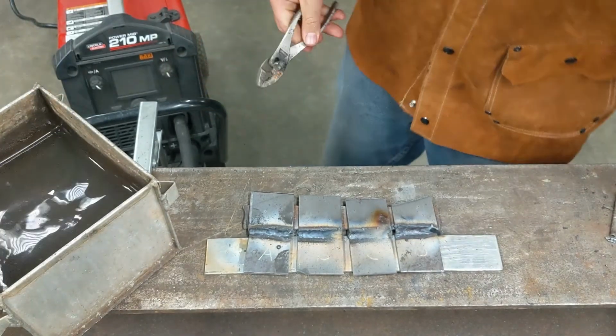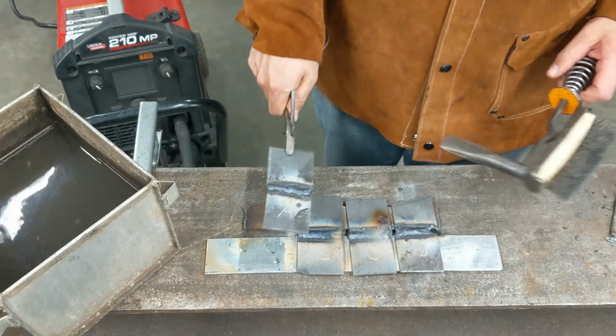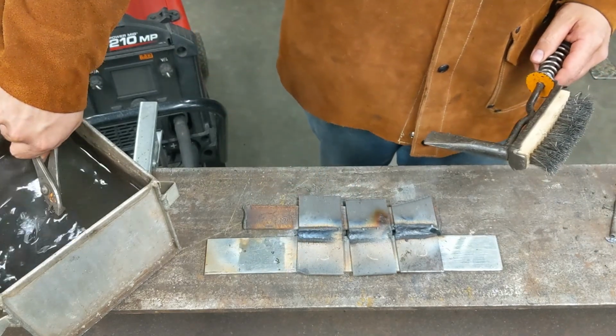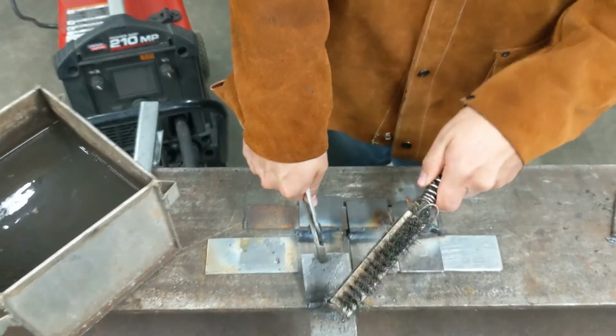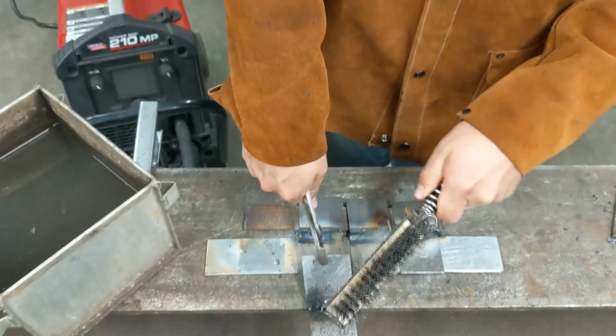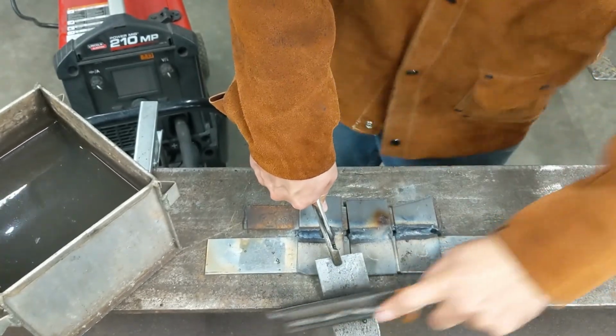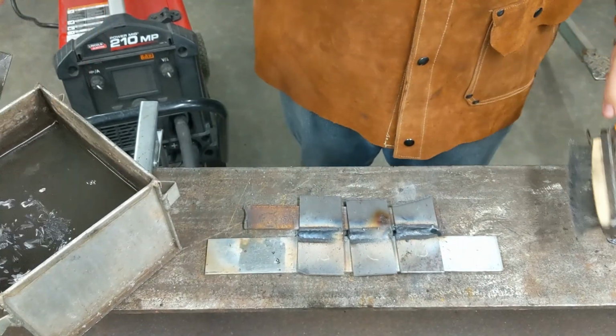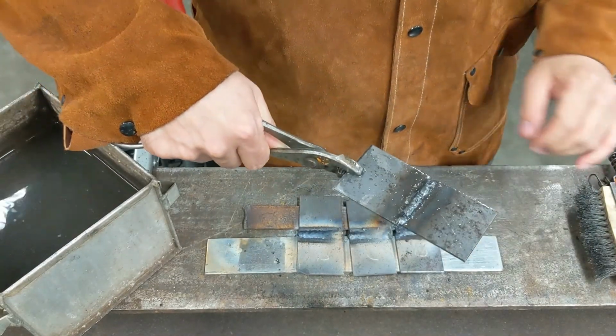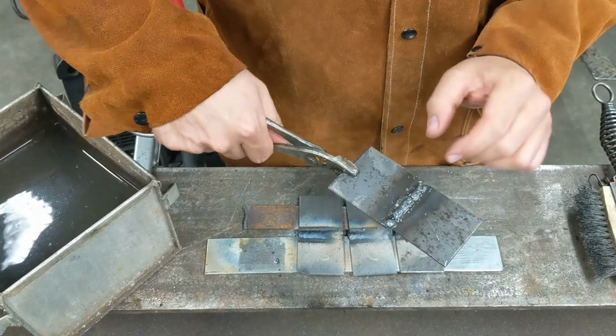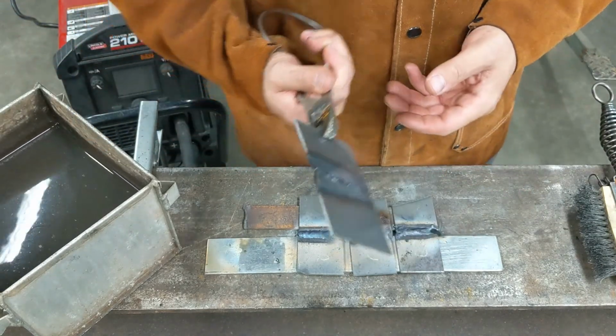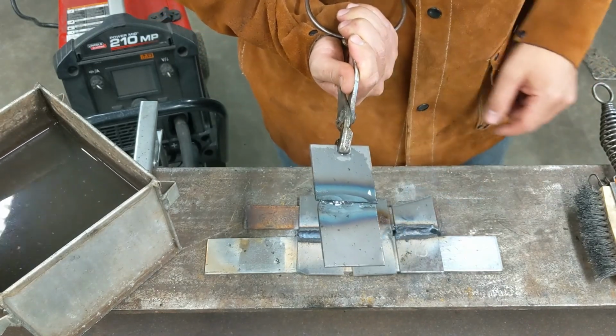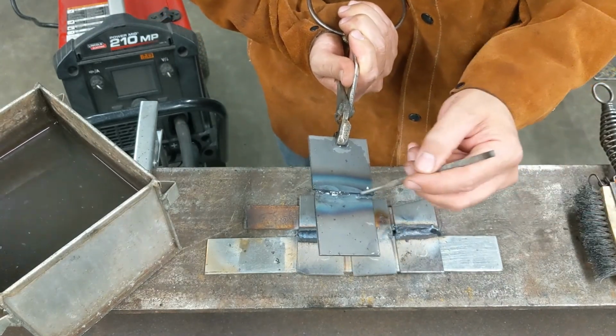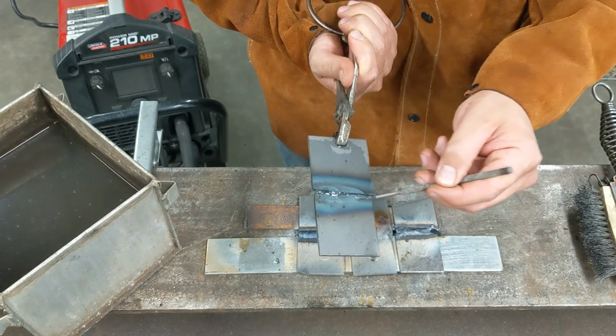Now I'm going to quench each weld. We'll take a look at it and then we'll break these welds. Our first weld has a relatively narrow and tall bead. It didn't have enough amperage to really burn into the workpiece. When we look at the opposite side, we can see that there's some discoloration, but really there's no weld that penetrated all the way through the workpiece.